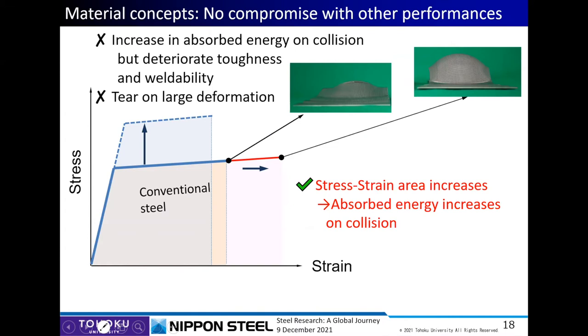So if we think about stress strain curves, in order to improve the crashworthiness, one option can be imagined by increasing the tensile strength, something like this. If you get this kind of enhancement of strength, you can get increased absorbed energy on collision, but this modification may cause some deterioration of toughness and weldability. And also we can get some tear on large deformation by this modification.